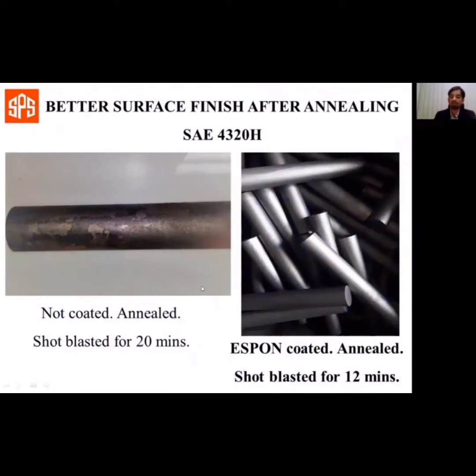Forging billets of SAE 4320H. You can see the extent of damage due to scaling after annealing. In spite of giving a shot blasting time of 20 minutes, the stains and the scaling has still remained. In contrast, the coated and annealed billets have a very good surface finish. Shot blasting time is reduced from 20 minutes to only 12 minutes, 40% reduction in shot blasting.